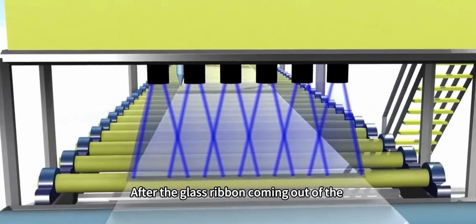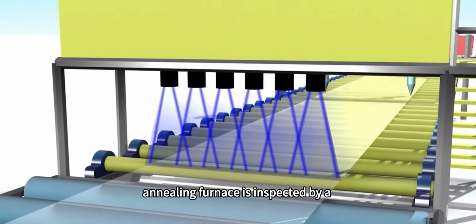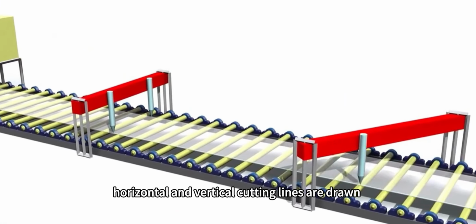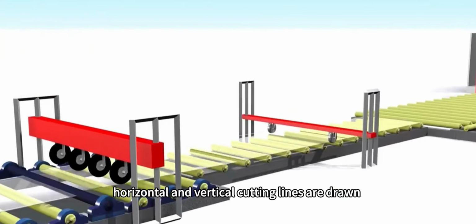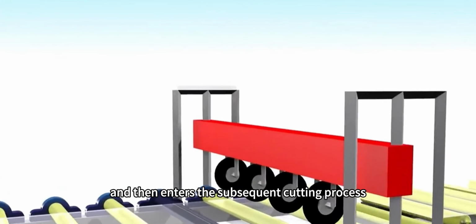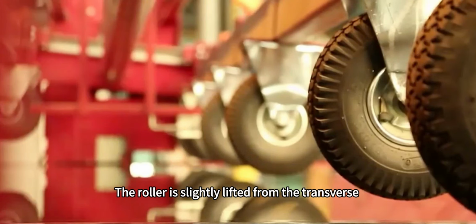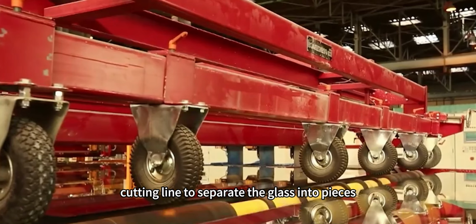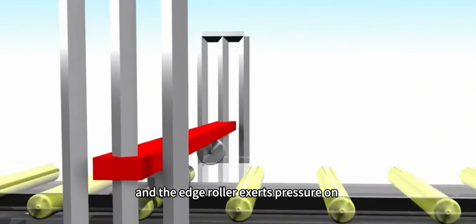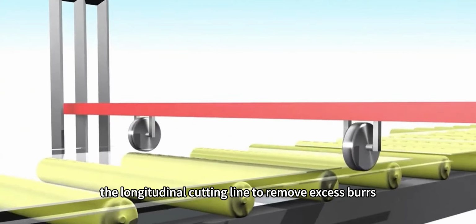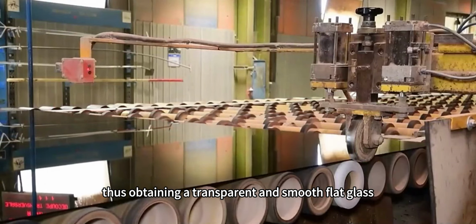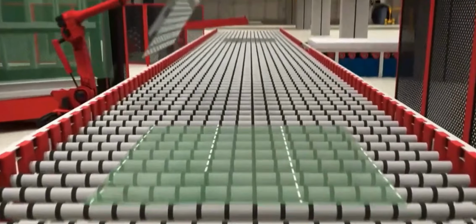After the glass ribbon coming out of the annealing furnace is inspected by a high-performance optical system, horizontal and vertical cutting lines are drawn and then enters the subsequent cutting process. The roller is slightly lifted from the transverse cutting line to separate the glass into pieces, and the edge roller exerts pressure on the longitudinal cutting line to remove excess burrs, thus obtaining a transparent and smooth flat glass.